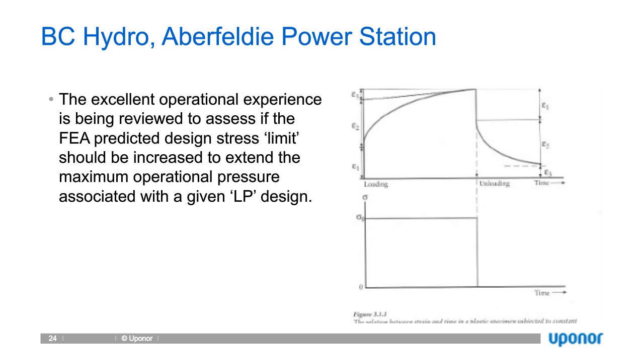I noted that the plots of time to failure are log-log plots. You see the same, which indicates that most of the deformation occurs early, and you're seeing that in this slide as well. On the bottom, we're indicating stress that's held at a constant level, and on the top portion here, most of the deformation occurs very early. So one would expect that inspecting this pipe at the 9-year point, most of the deformation that would occur in a 50-year or 100-year period would already have occurred.